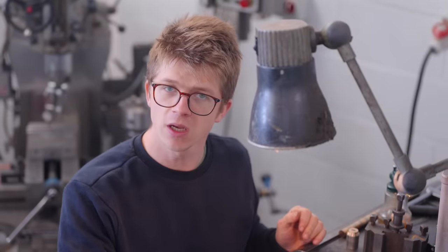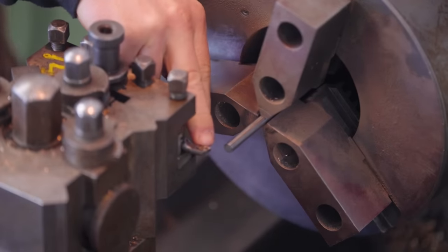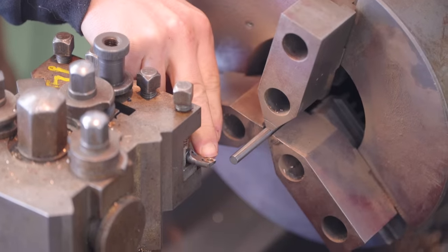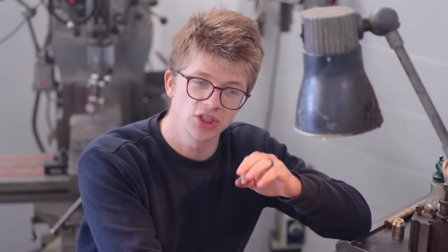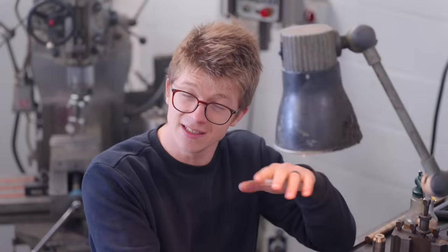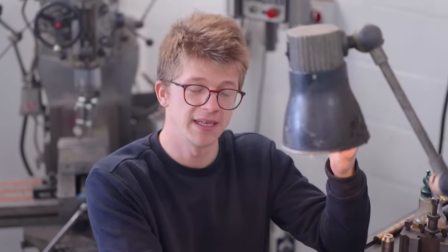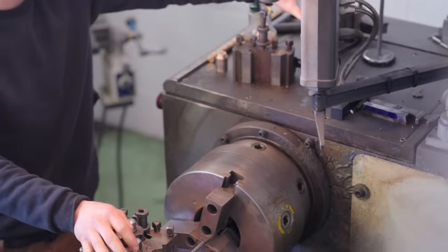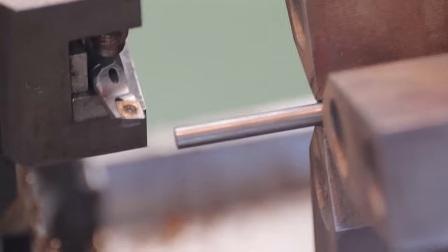Is it even possible to machine tungsten in this workshop? In my little research about machining tungsten, I found some things I already assumed — it's very hard and very brittle. But I've also learned some things I didn't know: it is meant to be possible with tungsten carbide tooling, like the little insert I have in now. As I assumed, it wears the tooling very quickly, so the reason I have this teeny weeny little one is it's the only tool I have spare inserts for. The really interesting thing I've learned is that at about 400 degrees Celsius, tungsten changes from its primarily brittle state to a slightly more ductile state. A lot of tungsten machining is done by heating the workpiece to 400 degrees Celsius — that might be what we have to do if it won't cut at room temperature. I have no idea about feeds and speeds. All right, we're going to start at a thousand RPM. Let's go.